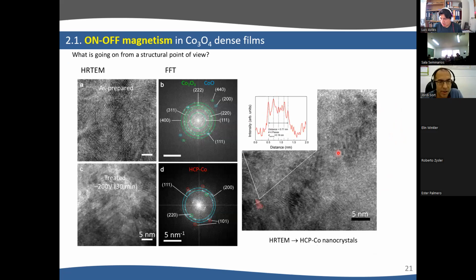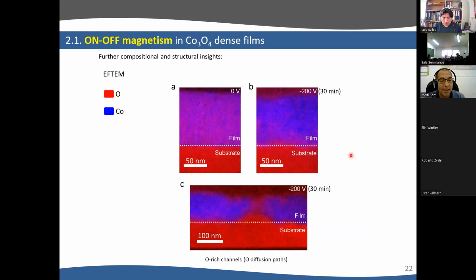To confirm this hypothesis, we performed high-resolution TEM. In the as-prepared material, you can see here that there are spots from Co3O4 and cobalt monoxide. And when we treat the sample at minus 200 volt for 30 minutes, additional spots appear in red here, and they correspond to metallic cobalt. And if you do the inverse fast Fourier transform, you can even find the location of these cobalt nanocrystals. Then, if we perform energy-filtered TEM, you can see that after treating the sample, there are regions in the layer that become rich in oxygen, and other regions become rich in cobalt.